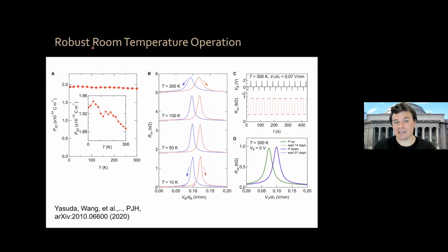All the other physics I told you about with superconductivity was at low temperature. This thing is actually robust at room temperature. You can cycle it thousands of times. You can wait months. The ferroelectric state, it's a good memory. This is in fact the world's thinnest out of plane ferroelectric, okay? It's less than 1 nanometer in thickness, and it's completely robust, okay?